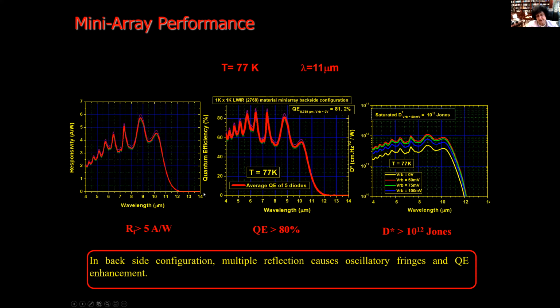You can see the mini arrays of the antimonide based, with the three important parameters: the responsivity, quantum efficiency, and detectivity. As we can see here, at 77K in backside configuration, this oscillation is related to the oscillatory fringes from the backside illumination. This result shows that at 11 micron already, with a very thin structure on gallium antimonide substrate, compared to the very sophisticated and thick buffer of the mercury cadmium telluride, this result is equivalent to the best of mercury cadmium telluride.